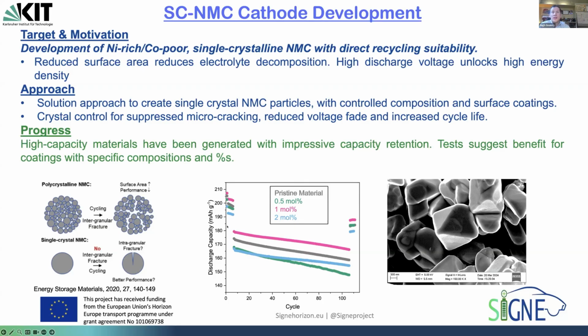So overall, the materials, these are a little bit old in terms of the data that I'm showing. There's some more that's been developed for publications, for example. There's much longer cycling stability now for these active materials. So these single crystal cobalt poor cathode materials seem to have really good long-term cycling stability. And again, the voltage fade that is associated very often with these high voltage cathode materials doesn't seem to be as pronounced as the previous generations.